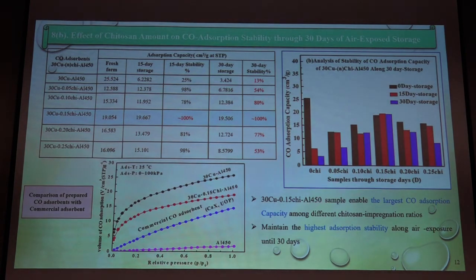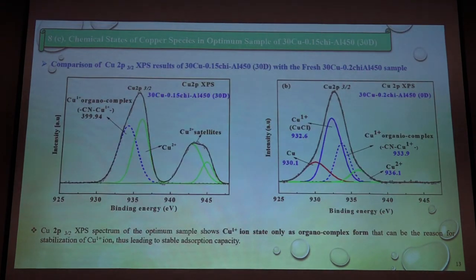And when I compared my optimum sample with the commercial samples, it is quite a good adsorbent. So afterward, I also analyzed the copper ion state in the optimum samples, and I found that most of the Cu1+ ion exists in the complex bond. That's why the copper and nitrogen complexation can keep the copper ion from being oxidized, by resisting the air.